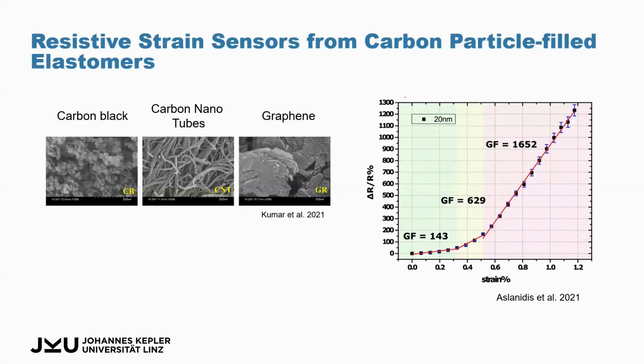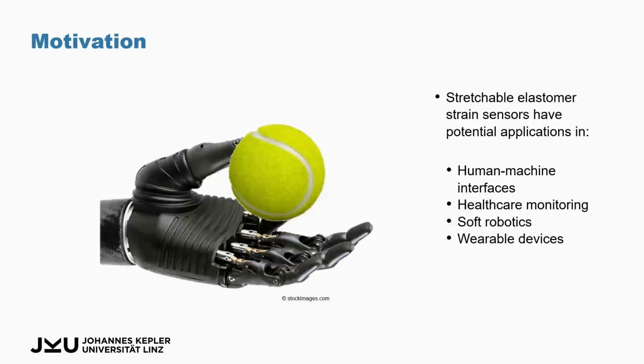So as we've already seen, if you put conductive particles into a matrix, or today I'm mostly talking about elastomers, most prominently PDMS or silicones, whether it's carbon black or carbon nanotubes or graphene doesn't really matter, you can get to a conductive system if you surpass the percolation threshold. And if you tune your material to be in that percolation area, for strain sensors, you can get to very, very high gauge factors or sensitivities, which make these materials very promising for a number of applications, ranging from wearable devices, soft robotics, but also for actuators themselves, such as dielectric elastomer actuators.